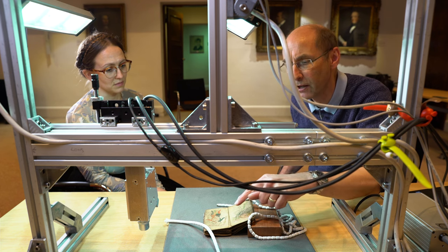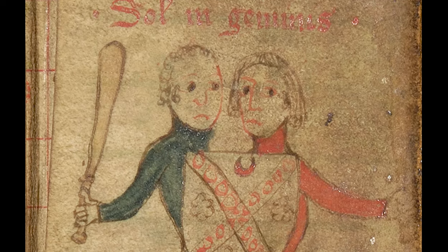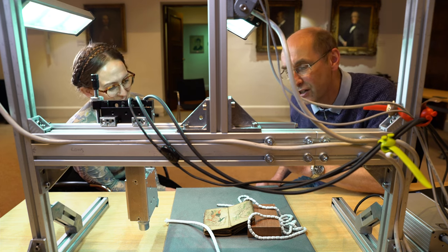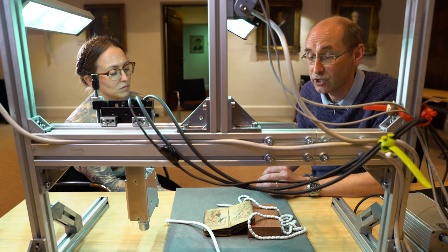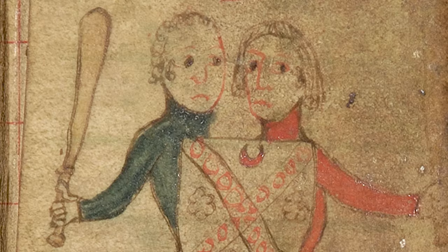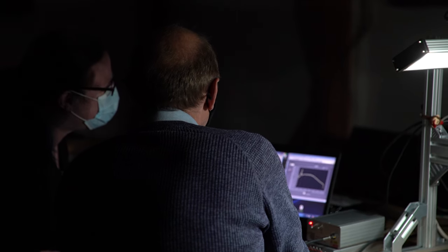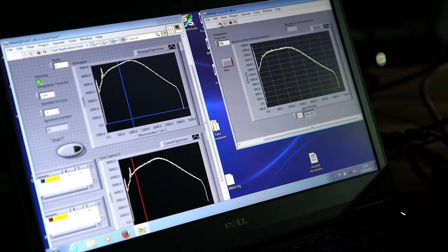What's really exciting is the club. You can see one of the Gemini twins holding up a club in his hand. It looks quite an unexciting, very dull yellow colour. But we found Orpiment in there — arsenic-3-sulfide — which is quite an unusual find in books of this period. It's not common to find Orpiment here. Of course, it's a highly toxic material as well, so it really is quite a dangerous club he's holding there. That's a pretty good spectrum, even though I say so myself.